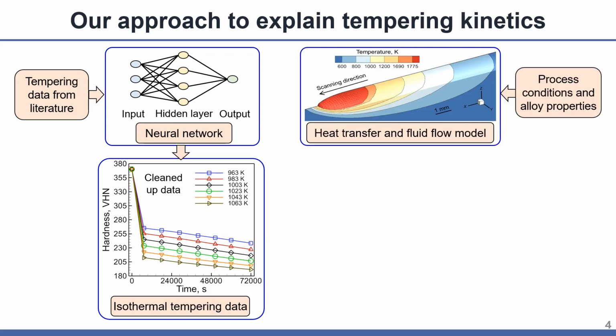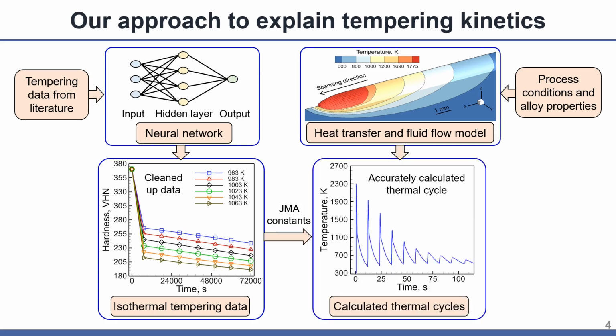A rigorously validated transient three-dimensional heat and fluid flow model of directed energy deposition was utilized to compute thermal cycles at various places in the part. Then the JMA equation was integrated by cumulatively adding small isothermal time steps over a computed thermal cycle to estimate the hardness. Because the hardness variation in a component is directly related to the fraction of phase change to another phase, the extent of tempering was computed from the calculated values of hardness.